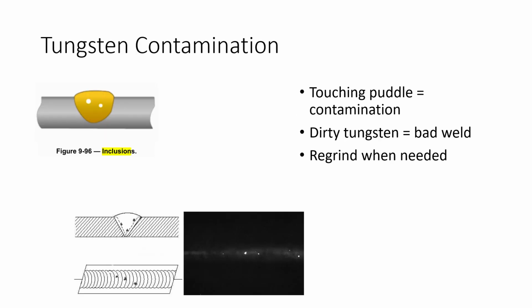What could go wrong? Well, tungsten contamination. If you dip the electrode into the puddle, you're going to get contamination. You're going to leave little molten globule balls of tungsten in the weld metal, and it's going to show up on an X-ray. And what else could go wrong? Well, if we've got dirty tungsten, we can end up with a bad weld. So we need to regrind when needed. We can't limp this thing along with dirty or contaminated tungsten. Got to be a grown-up. Cycle out the tungsten or clean it up.